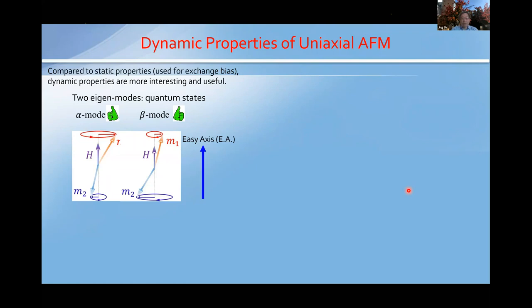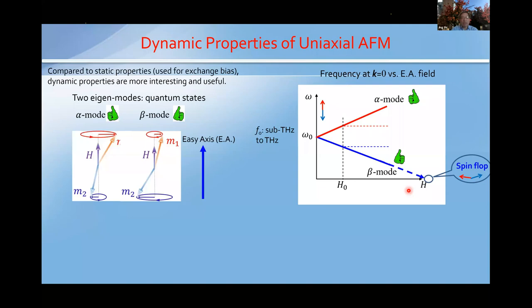So here, I just want to show that they're simple in uniaxial antiferromagnets. There are two eigenmodes for spin precession. Let me use alpha for the right-hand and beta for the left-hand spin precession modes. These two modes have the same energy under zero magnetic field, which is determined by the exchange interaction and anisotropy energy.